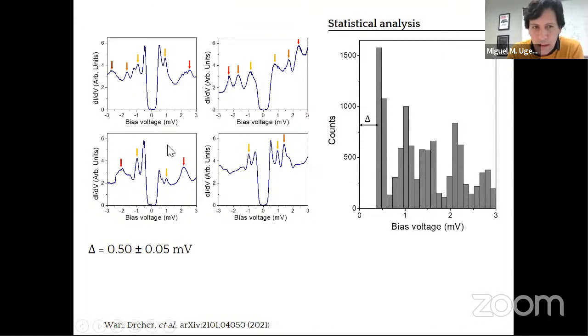The first one corresponds to the coherence peak, to the existence of the coherence peak at an energy of 0.5 milli-electron volts. Keep in mind that even when I describe this as a superconducting gap, it's not the BCS gap, it's just the distance between the Fermi level and the position of the superconducting gap. That's why it's a bit larger than the BCS fit, but it's okay. We have used this definition in general.